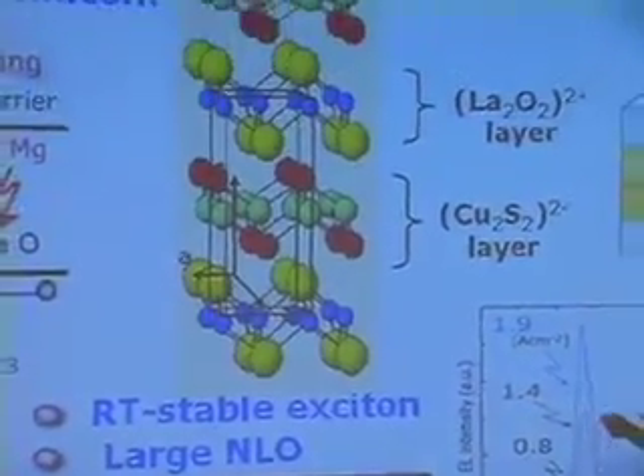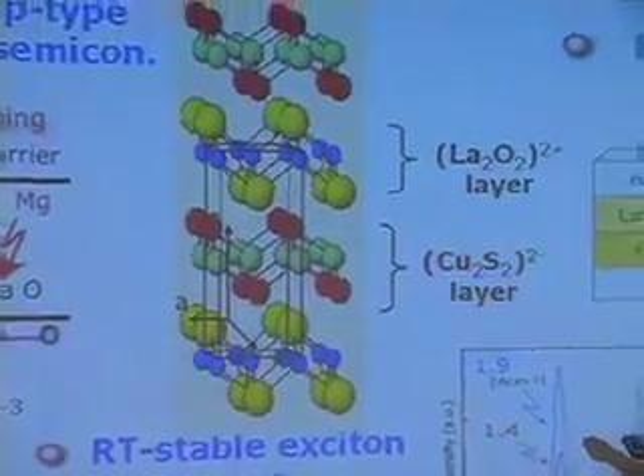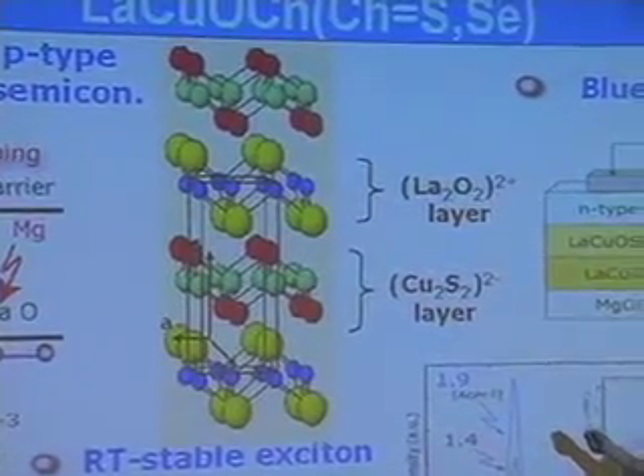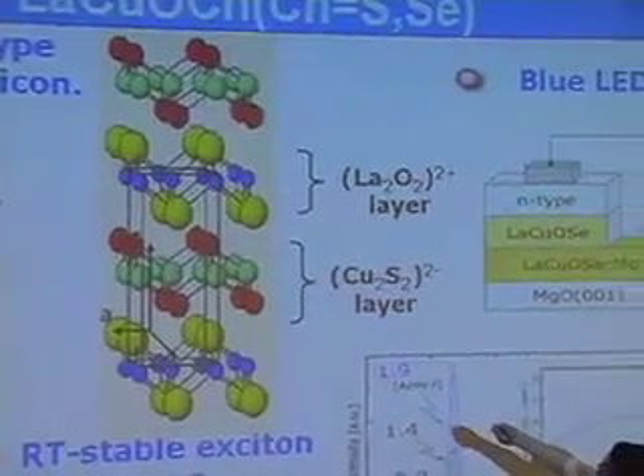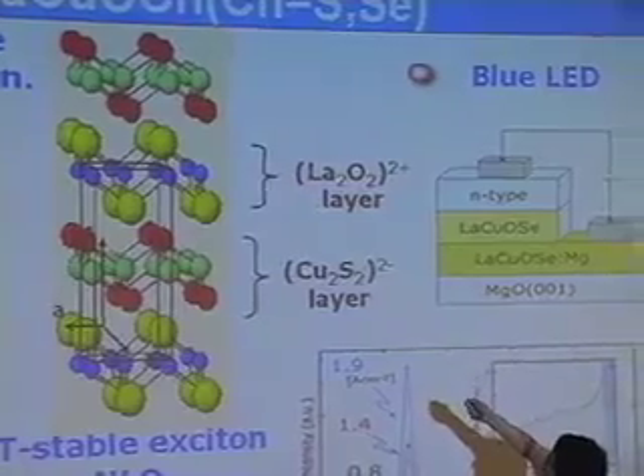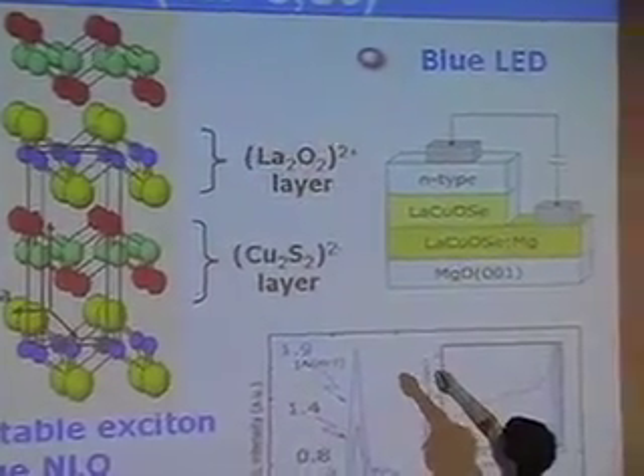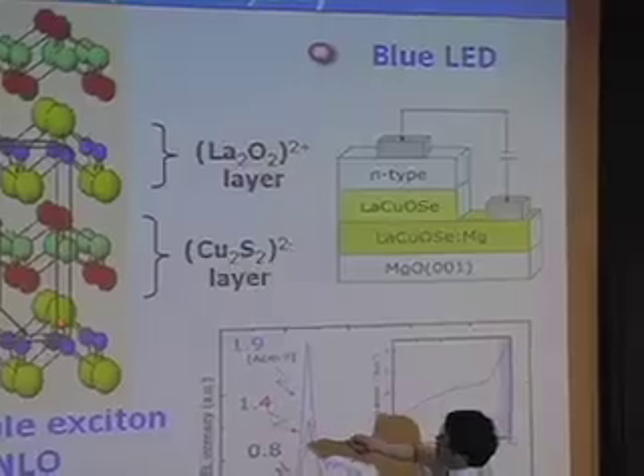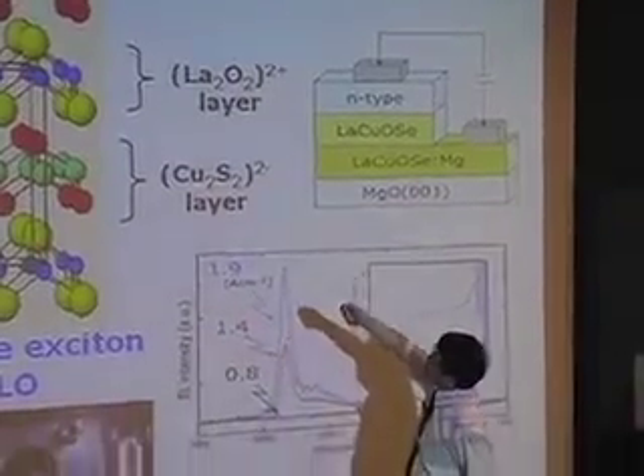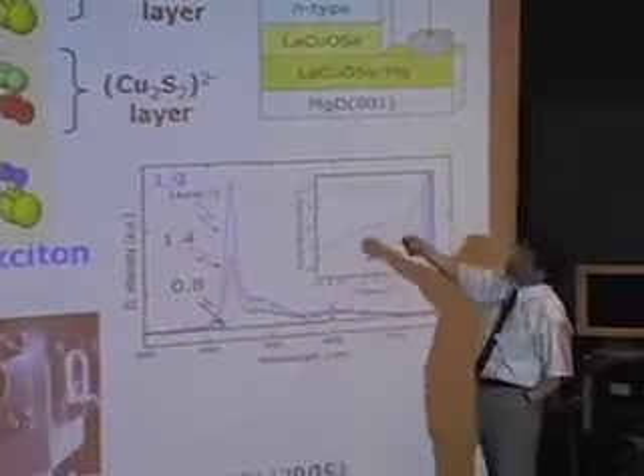This is a layer of copper sulfide, where copper is a 1-plus ion, so the net charge is double minus. To compensate the charge, we adopted lanthanum oxygen layers with a +2 charge, so the minus and plus charge layers are alternately stacked along this direction.